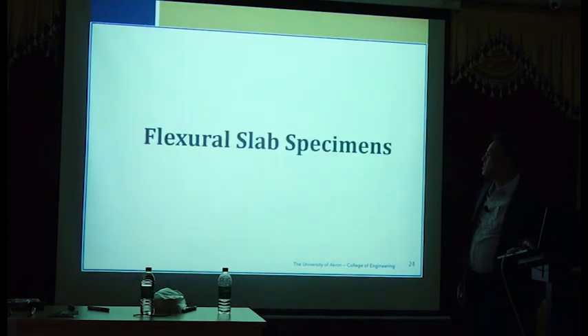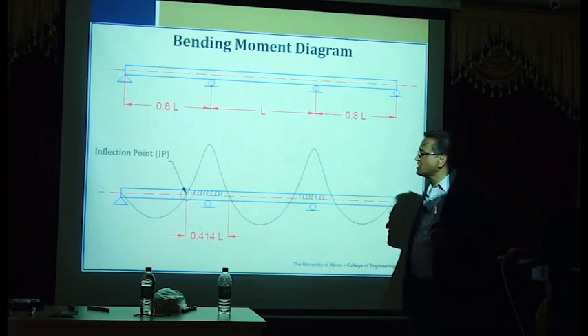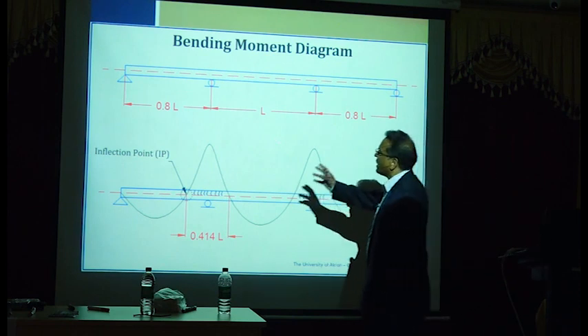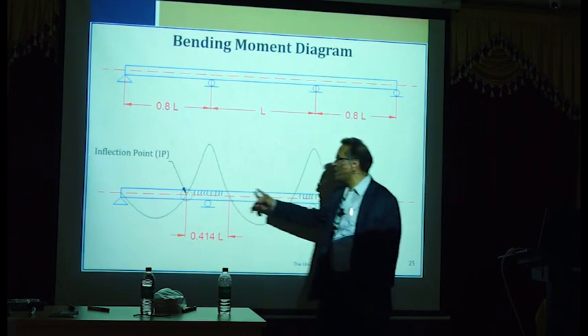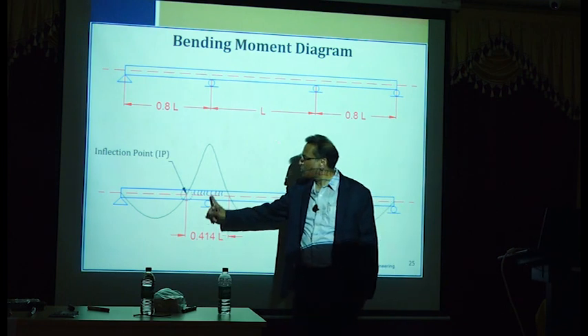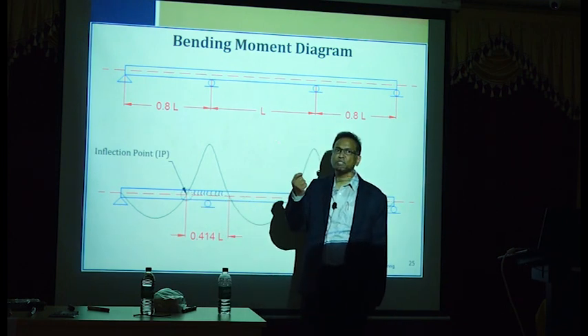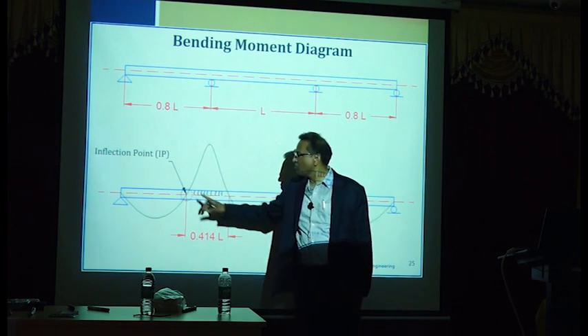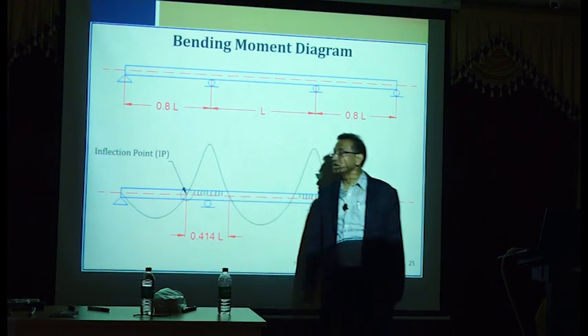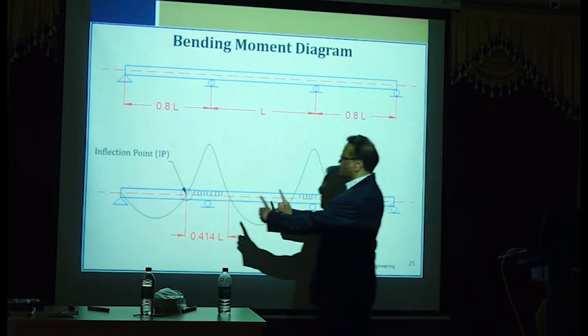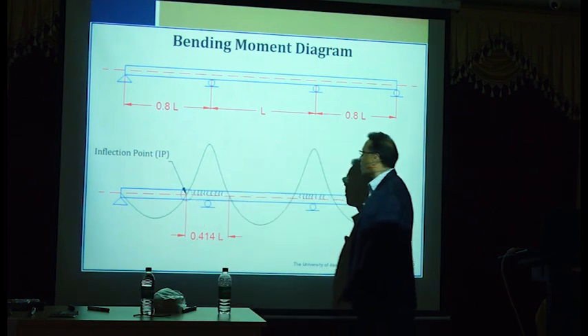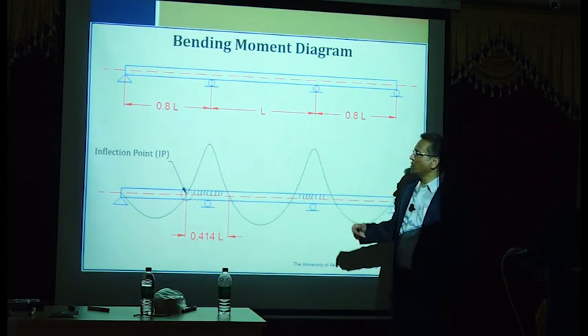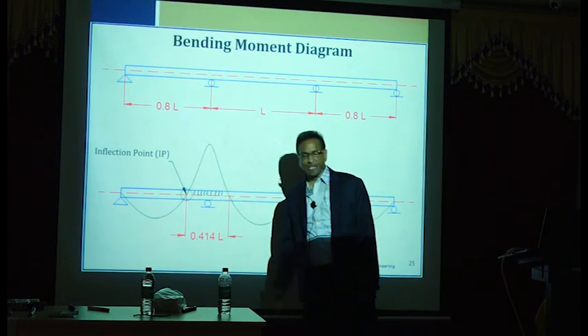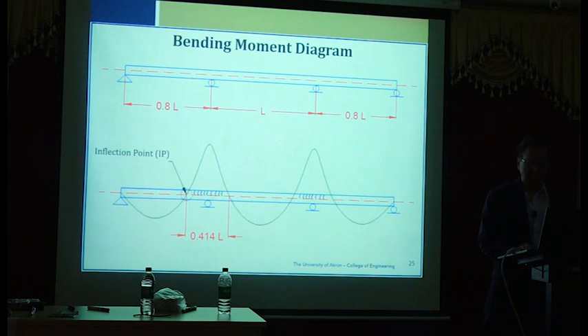Then we also did some flexural tests, beam tests. So in the beam test, we actually simulated the 3-span bridge by testing this part only. So that's a 3-span continuous bridge. So you have support here, there is inflection point here. Inflection point is the point of zero moment. So inflection, zero moment here, zero moment here. We isolate this element, and we actually tested everything to represent this small element. Even though it's a very long bridge, very very long bridge, we were able to test only this small length, and then we were able to get the results that correlate with full-scale tests.